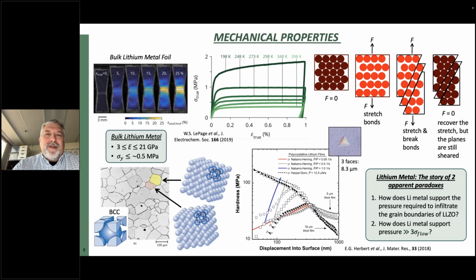All right, and so here is another apparent paradox. So this plot shows the hardness as a continuous function of depth, and it's over the range of about 40 nanometers out here to a micron, right? So I'm not going to get into the details here, but the conundrum is that based again on this uniaxial stress strain curve for bulk lithium metal, the hardness at room temperature should be coming in at around 3.5 times or so the yield stress. So something like 1.5 MPa, right? And yet here we are, take a look at the numbers on the y-axis, right? We're as much as 2 orders of magnitude higher. So again, the million-dollar question is, how on earth does lithium support these high stresses, yeah?